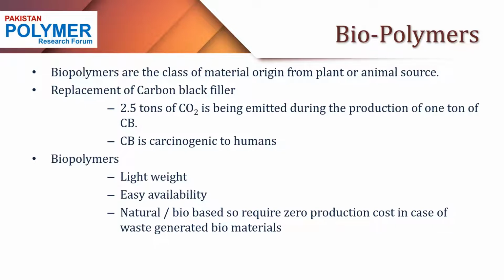Carbon black causes 2.5 tons of carbon dioxide release during the production of 1 ton of carbon black. That is a very huge quantity. Along with this, carbon black is carcinogenic to humans. Because of the large free volume or incorporating capacity of rubbers, we add a high concentration of carbon black or filler, and that can cause cancer.